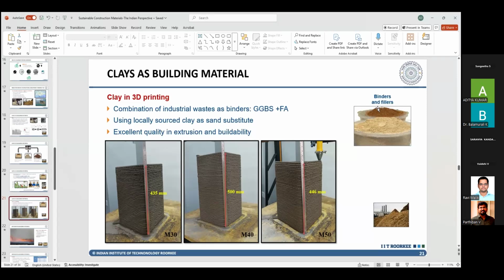So clay is something that has very easy acceptance in the construction industry, because even historically, if you see, surkhi is a common word that has been used, and surkhi was a very common ingredient that was added along with lime, because bricks were being manufactured millennia ago, and lime was available readily to them. So they used to add surkhi to lime to solidify their mortars. And this is nothing but a pozzolanic reaction happening. You use lime, which is calcium hydroxide. You use surkhi, which is nothing but a burnt clay, which is metakaolin to some extent. You add the two and you have pozzolanic reactions. You have insoluble hydrates, which will not wash away with water.